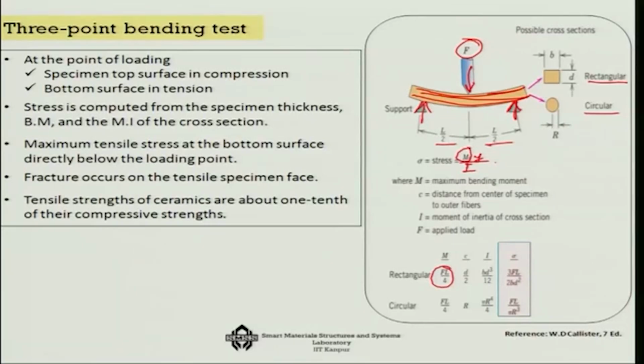And then we can also note down, corresponding to load, the stress at which the failure occurs in the sample. Generally the failure is in tension. Tensile strengths of ceramics are about 1/10 of their compressive strengths. So, we expect that the failure starts from here at the bottom, because the resistance to tensile stress is much less in comparison to the compressive stress.